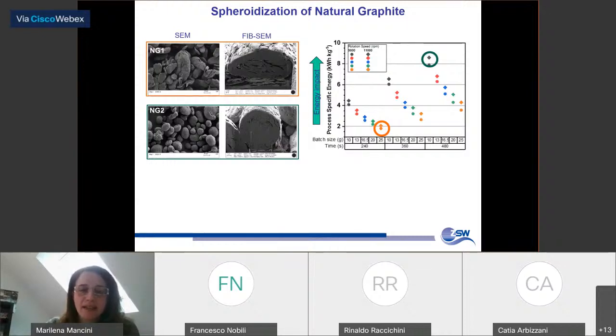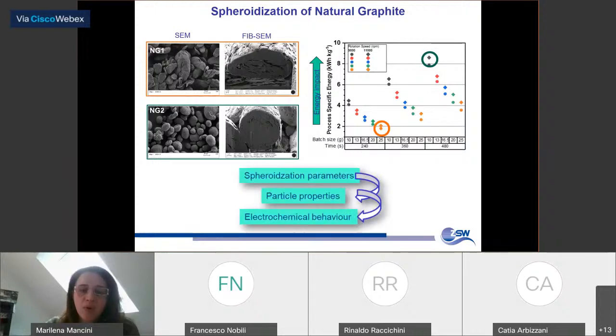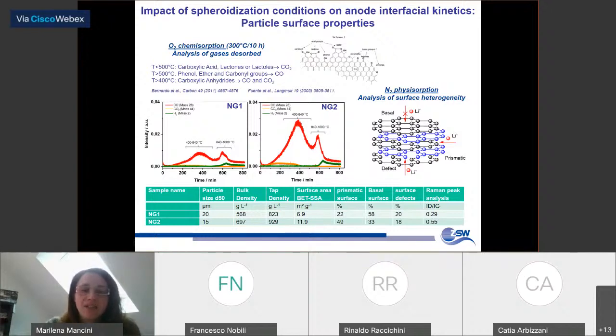But nevertheless, there is a difference between these materials, and in the whole range of investigated parameters, we could analyze all the different properties. The aim was to find the relationship between spheroidization parameters, particle properties, and electrochemical behavior. In particular, beside the classical techniques and the standard analysis of density, particle size distribution and surface area by BET analysis, we have also applied oxygen chemisorption to analyze how reactive the surface of the graphite particle is after the treatment.